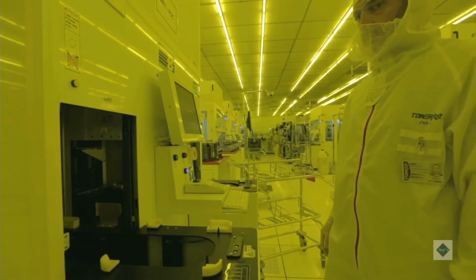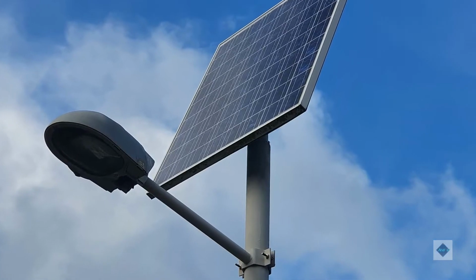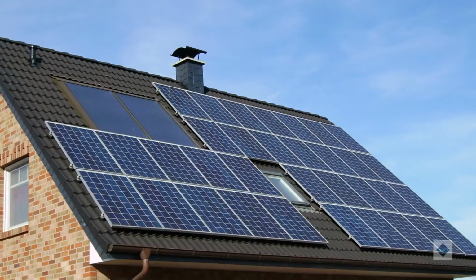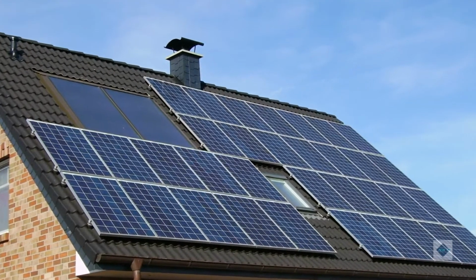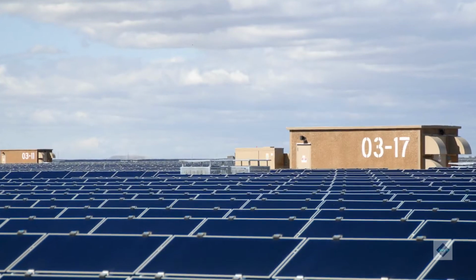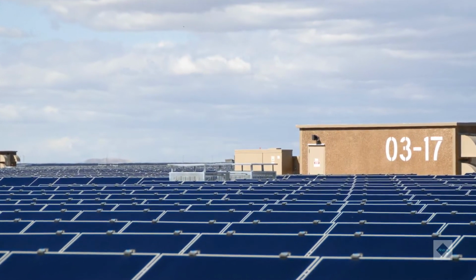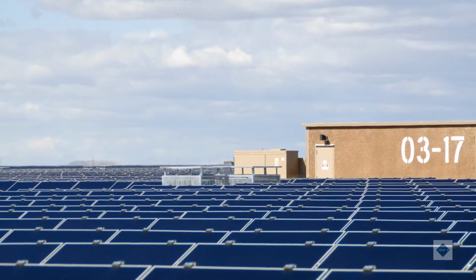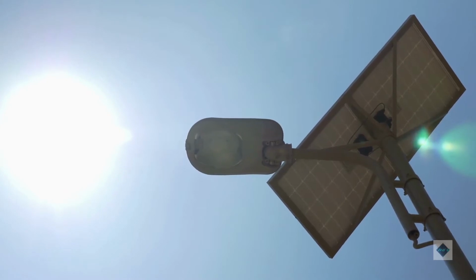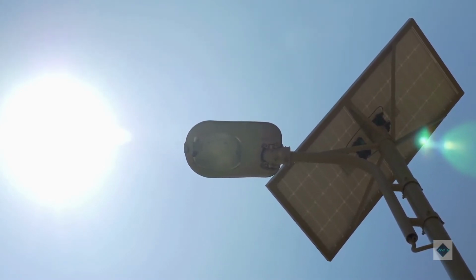As the solvent dissolves, the mixed ingredients crystallize in a thin film. Mohite's group has made 2D perovskite films in this manner for years, and though the films appear perfectly flat to the naked eye, they are uneven at the nanometer scale. In some places, the film may be a single crystal in thickness, and in other places, several crystals thick. You end up getting something that is completely polydisperse, and when the size changes, the energy landscape changes as well, Mohite said. What that means for a photovoltaic device is inefficiency, because you lose energy to scattering when charges encounter a barrier before they can reach an electrical contact.